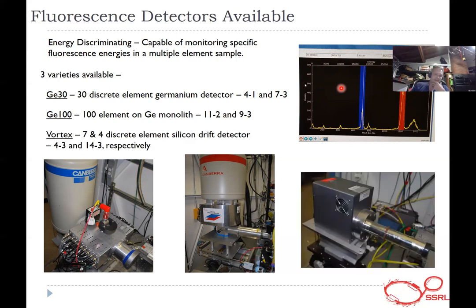And then we also have vortex detectors. We have a 7 and a 4 element, and these are nice. Again, you have the same problem with stopping power. Germanium detectors are better at high energy, meaning you create a photoelectron for photons that are higher energy, whereas in a silicon situation, the photon might go straight through and you don't count it. And so the silicon drifts, they're generally better below 15 to 20 keV.